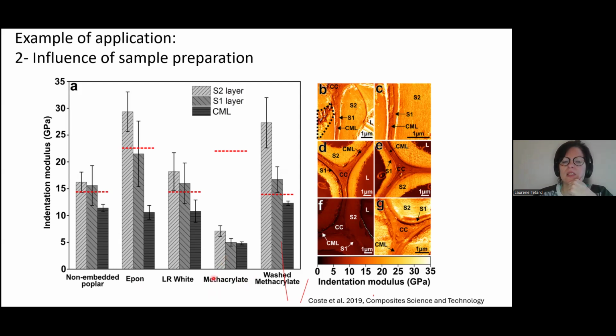For instance, here in this graph, you see the mechanical property of non-embedded poplar that was sectioned without any resin. Those are the mechanical properties for the different cell walls: S1 is this layer here, S2 is the larger region, and the CC is the cell corner here, which the entire region we call the compound middle lamella, CML. So this is the range of mechanical property we probe when the wood is not embedded. But you see that with every resin, we modified the mechanical property. In some cases, the resin diffused in the S2 layer.